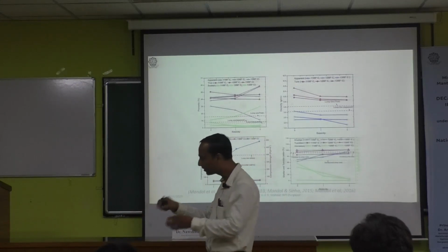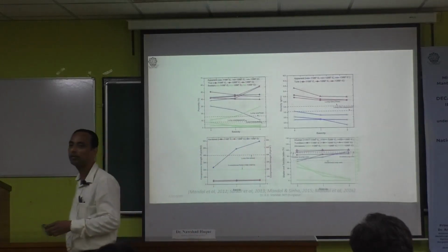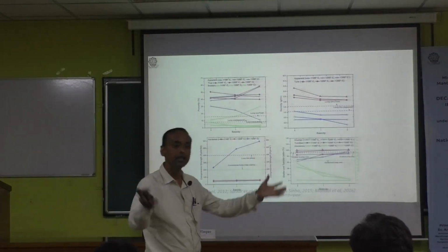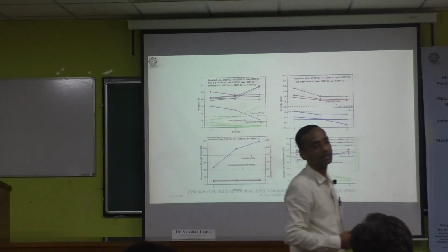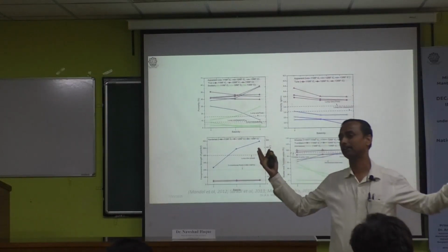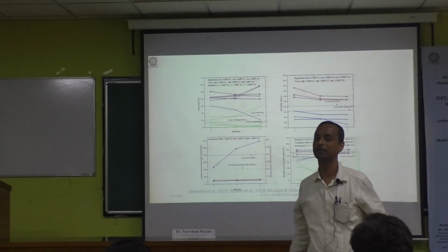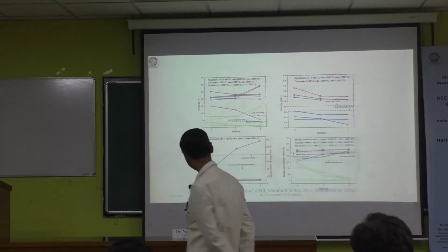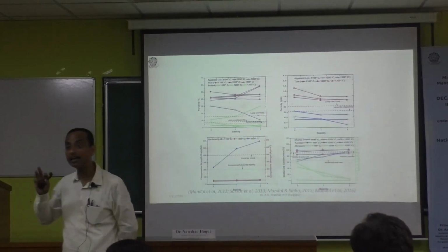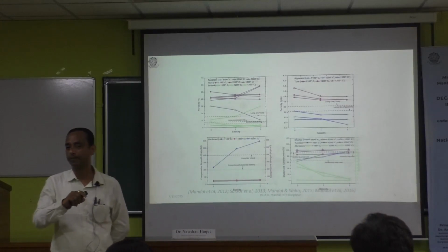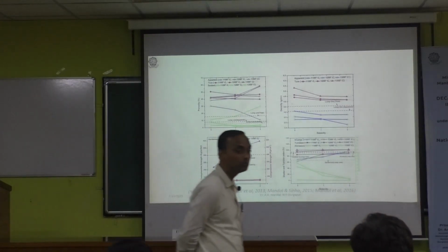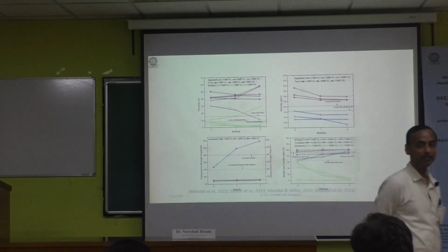Okay? Then if you keep these pellets in the open atmosphere, what will happen? It will again take up the moisture. Again it will expand, and when it expands, it will break the pellets. It is therefore hygroscopic in nature, these pellets. Then how to tackle this problem?